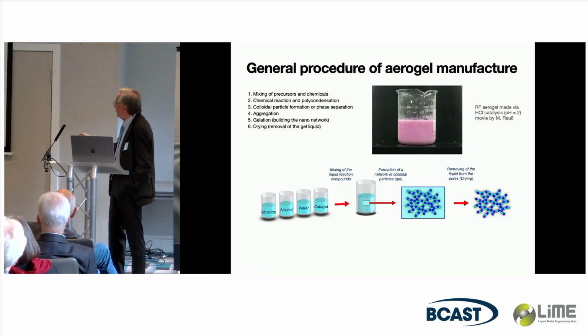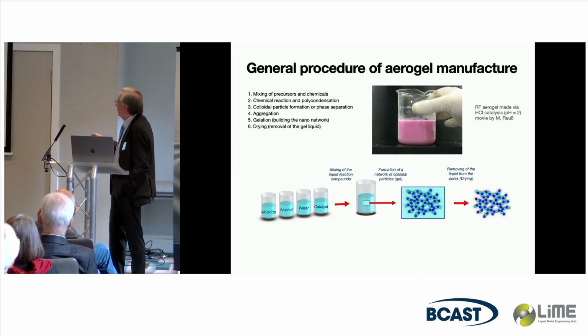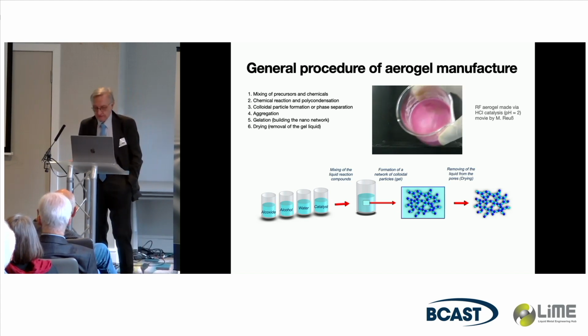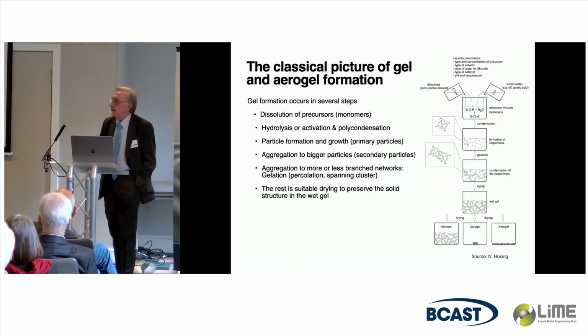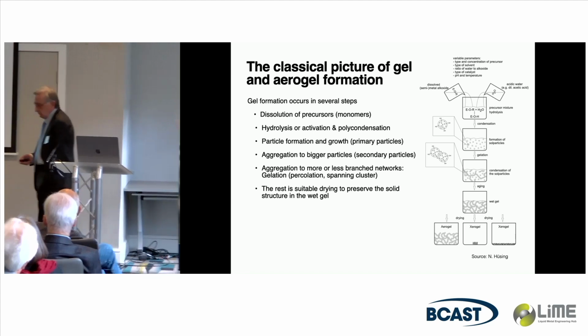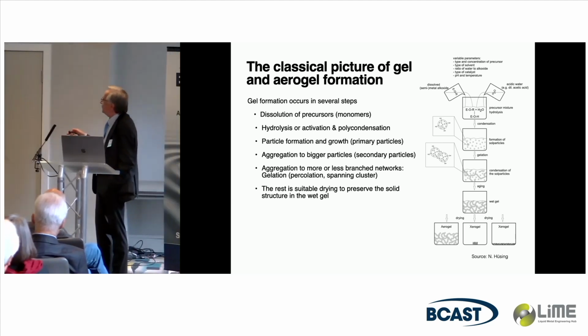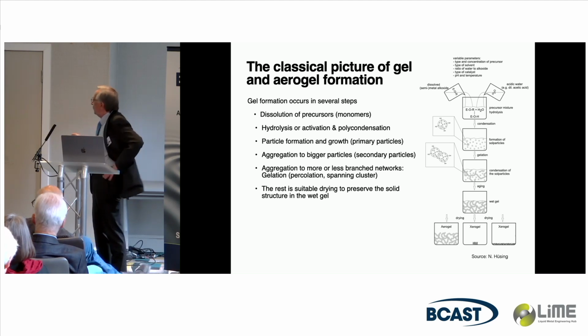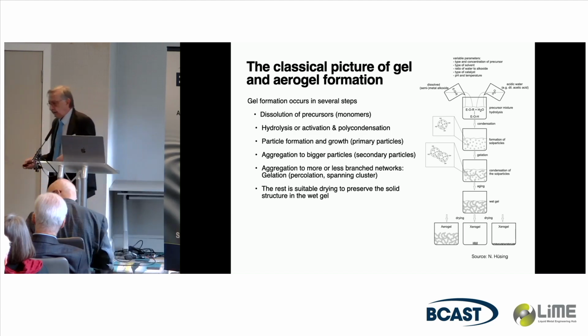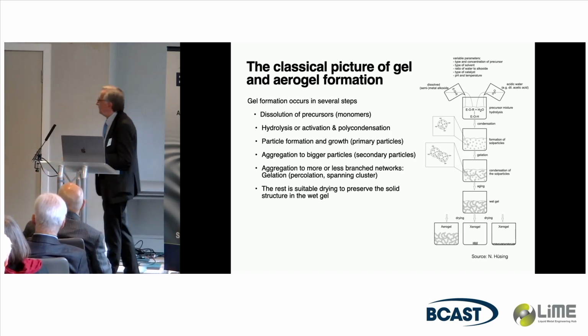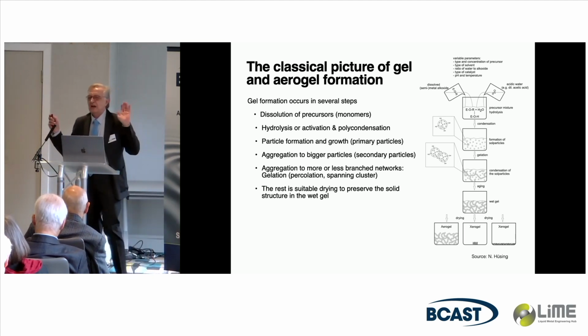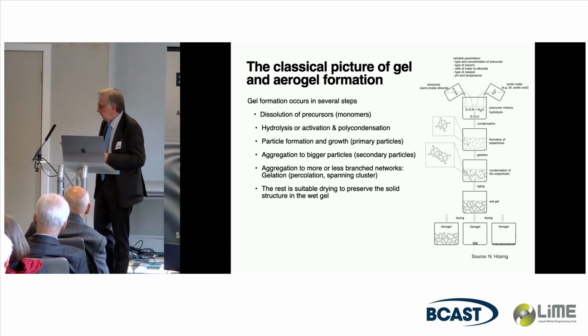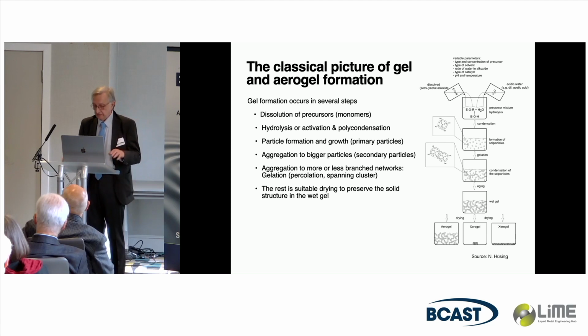So what we have at the end is a network of particles, however they aggregated, and you just have to remove the liquid, and you get out of that an aerogel. Classical idea. Therefore, my first link to immiscible alloys is: you dissolve the monomers, or what you call precursors. You have hydrolysis for silica activation and a polycondensation reaction. So somehow particles are formed. They aggregate by whatever mechanism to a spanning network. It's a wonderful idea of percolation, spanning clusters, branched networks. And if you do that carefully, you can preserve, hopefully, the solid structure in there.